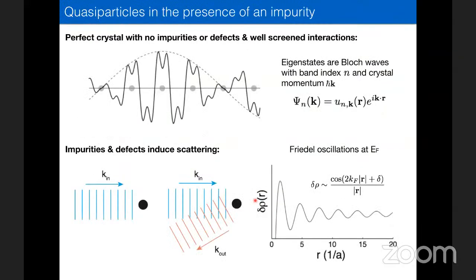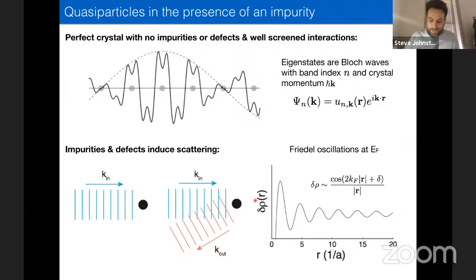Okay, so quasiparticle interference, just to remind you: when we think about itinerant states in a system, we're thinking in terms of Bloch electrons, things with well-defined wave-like properties. The Bloch states are eigenfunctions of the periodic lattice. But as you know, if you introduce impurities, the Bloch states are no longer eigenstates, right? And you'll start to introduce scattering off of these defects. So you can have a Bloch wave propagating along, it encounters a defect, it'll scatter, and these incoming and outgoing waves are going to interfere with each other and create modulations in the density. And when these are Bloch waves at the Fermi energy, the oscillation patterns that you create are nothing more than the usual Friedel oscillations that we teach in classes.